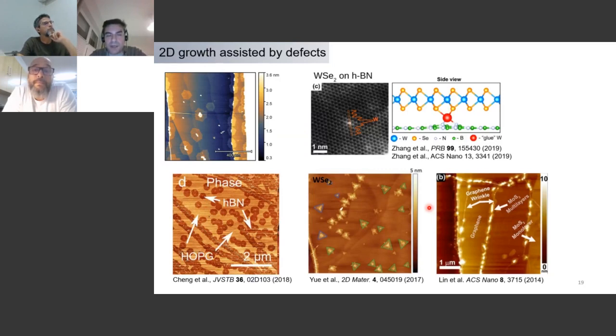That's why I mentioned in the beginning, if you start transferring graphene, for instance, you grow graphene on copper, transfer to SiO2, and I'm not an expert on that, but I know people working with that, and they honestly tell me that it's not so reproducible as in the case of silicon carbide epitaxial graphene. So in this case, we are quite lucky, because both MBE and the furnace for epitaxial graphene lead to very reproducible samples. Yes. Okay.